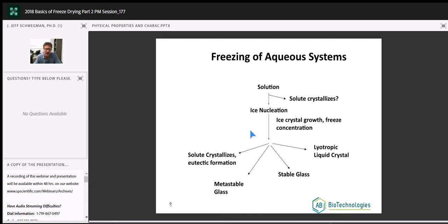Now, as we continue to cool down, the ice crystals are growing because they're pulling water out of that interstitial space. And when they do that, we super concentrate everything in that formulation within that interstitial space. This can be a damaging environment for certain unstable molecules. Well, finally, we hit a concentration and a temperature where one of four different things is going to happen. If we've got a crystalline species, it'll go ahead and form the eutectic, again, with the remaining water in that interstitial space. If it's not going to form a crystal, but it wants to form a glass, it'll solidify.